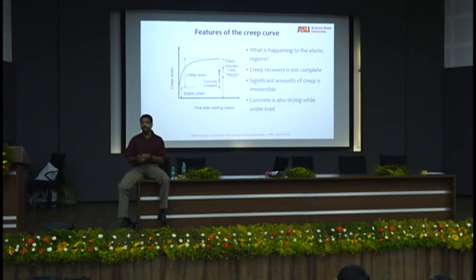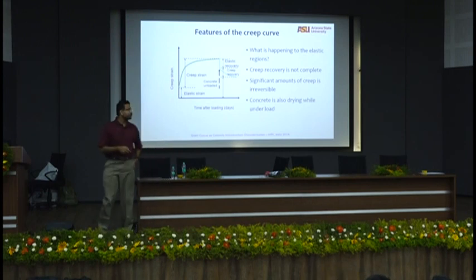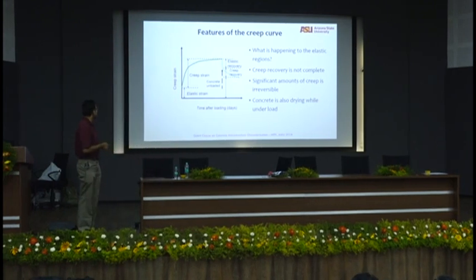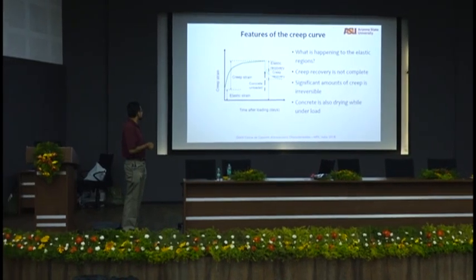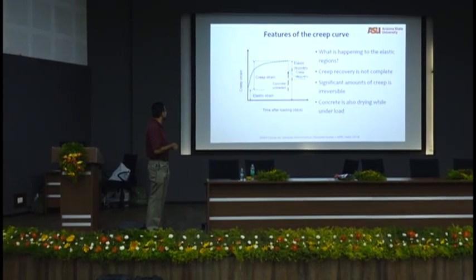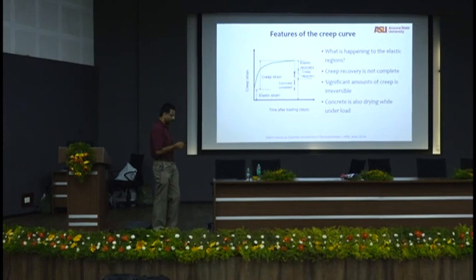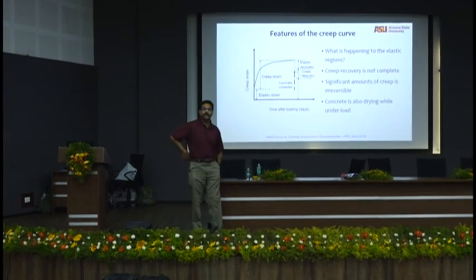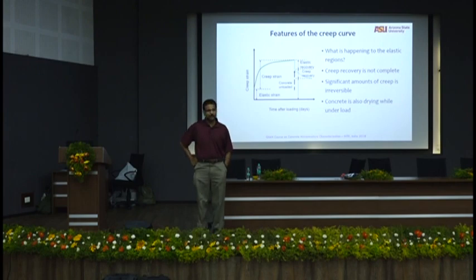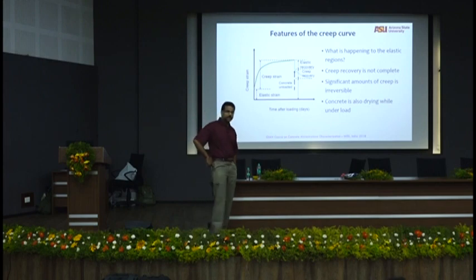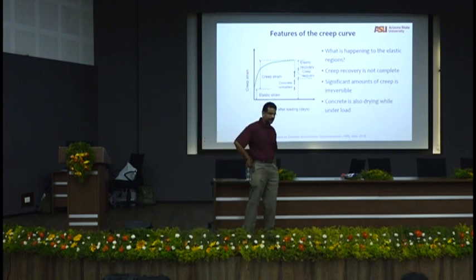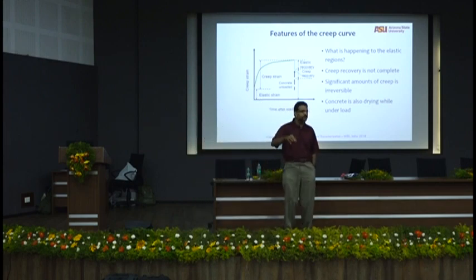Okay. Very similar to shrinkage, you can't recover creep completely either. You can recover some amount of creep. You have elastic recovery and then creep recovery, but a lot of creep is irreversible. Remember, when you talk about shrinkage and creep, while you are having creep, the concrete is also drying along with it, right? Drying shrinkage is happening, that's a volume change. Creep is a load-induced volume change. So now you have a combination of load-induced and drying-induced volume change.